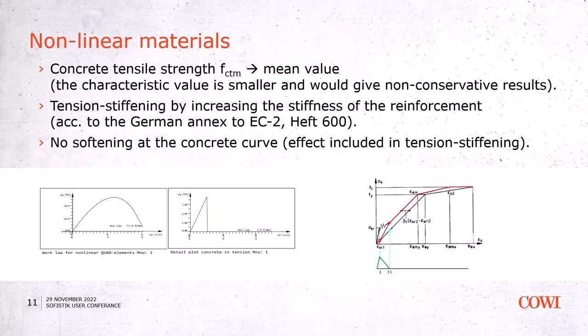Looking at the stress-deformation curve of the concrete in tension: it goes upward toward the tensile strength, then descends toward zero — this descending part is called softening. Since tension stiffening is already included by adjusting the reinforcement stiffness curve, we disable this softening part in the concrete curve to avoid duplicating and adding too much stiffness to the system, which would be unrealistic. So we operate with the curve going up to the tensile strength peak, then directly down to zero.